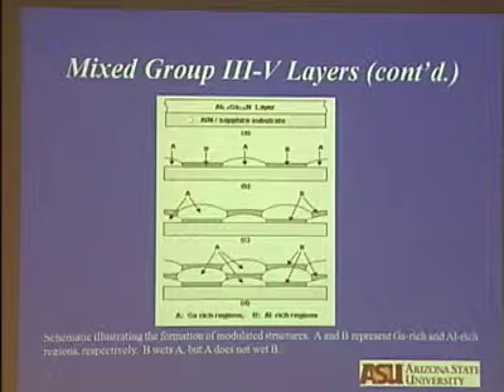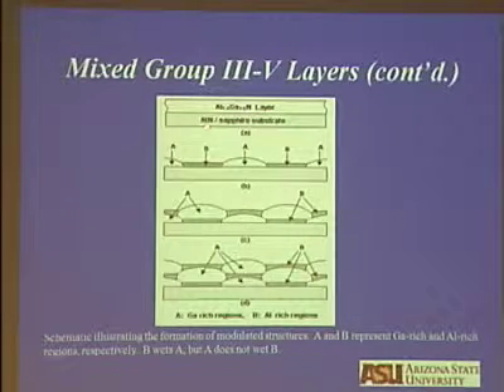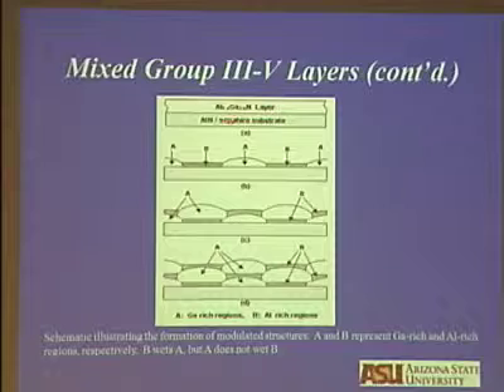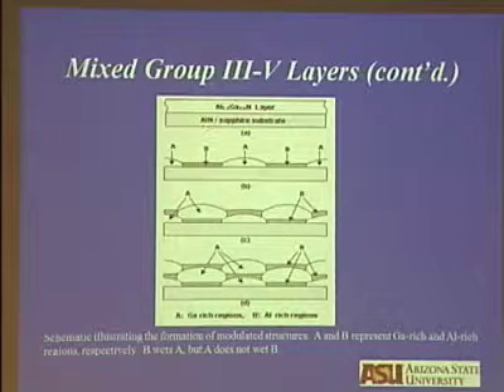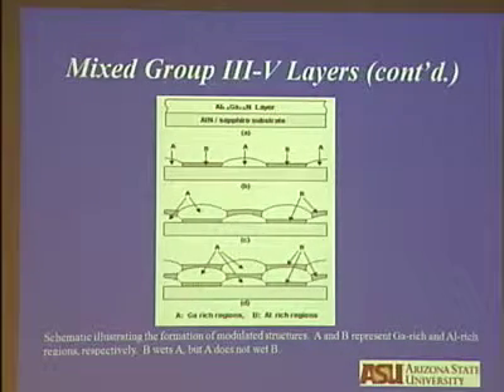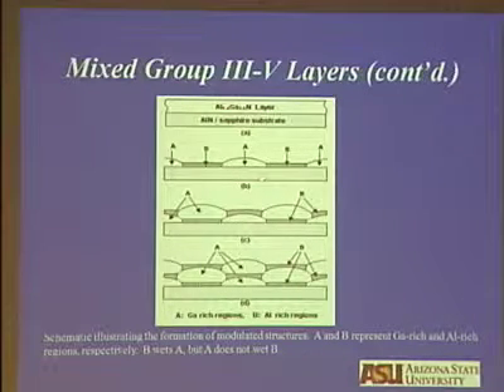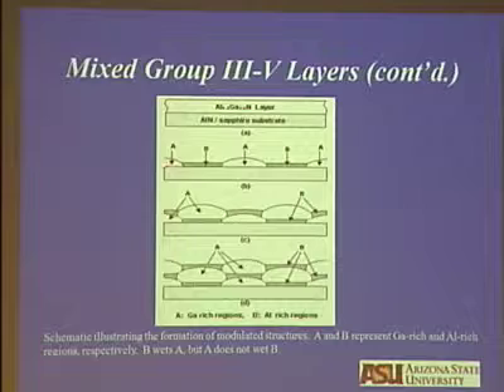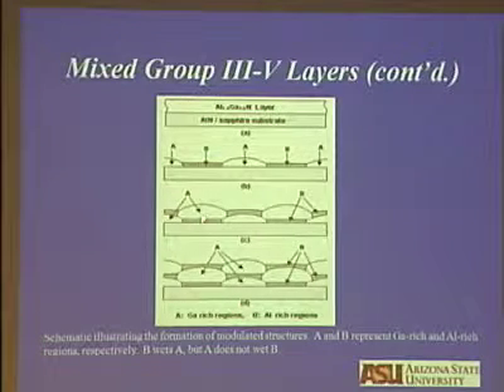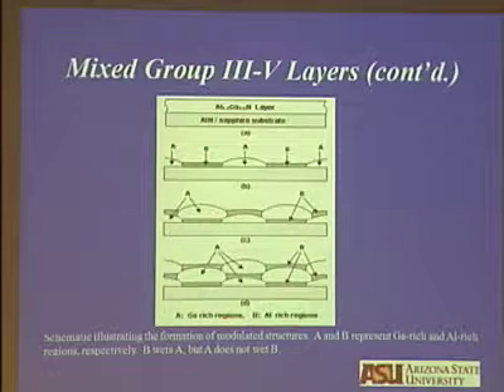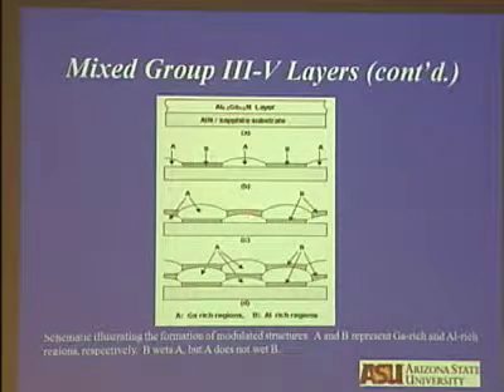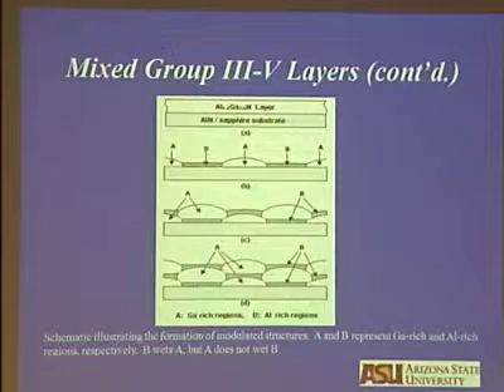You start growing aluminum gallium nitride on aluminum nitride on sapphire. This is a sapphire substrate. This is the buffer layer you grow on it. And we showed that these layers phase separate. The aluminum-rich regions wet the underlying aluminum nitride, but the gallium-rich regions don't wet. And that's what is illustrated. Their structure is shown here. You now deposit on these. There is an asymmetry in wetting behavior.